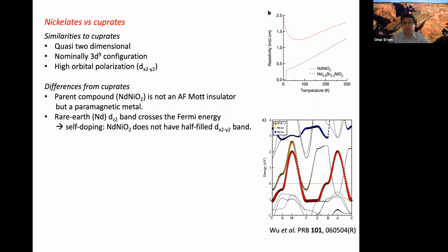So this is one of the main differences from cuprates: in nickelates, there is an extra band, which is weakly interacting because it has very low density, that crosses the Fermi energy and coexists with the strongly interacting dx²-y² band. As a result, even though it's nominally 3d9, this leads to self-doping, because some of the electrons go to this rare earth band. So the parent compound is not really d9, it is self-doped. It's actually less than d9. Another interesting thing, first raised, I think, by George Sawatzky, is that you have a weakly interacting band coexisting with a strongly interacting band. This really sounds like heavy fermions, okay? And I will come to that mainly in the second part of my talk.